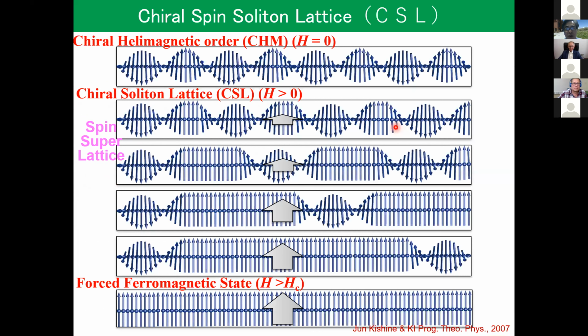This is a cartoon view. At zero field, there is a helix, but if we apply the magnetic field perpendicular to the helical axis, the pitch increases, and increases, and finally goes to an infinite value. They smoothly go to the forced ferromagnetic state. But in this situation, we can count the number of these defects. This is a soliton. We call it a soliton.